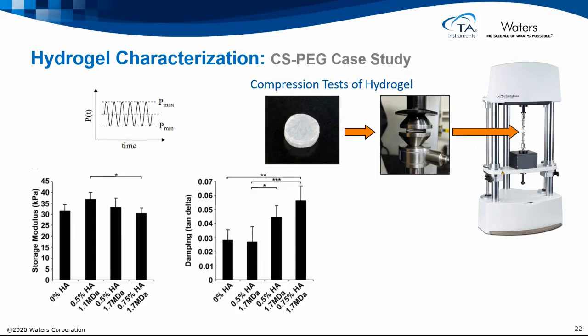Okay, here's a couple other results. This is a little bit more complicated yet. Before, we just did a compression ramp in displacement, which is strain, and measured the force, which is stress. Now they did an oscillating study. This allows you to oscillate displacement on this same material, a compression cylinder or disc, and measure the modulus by looking at the amplitude of force compared to the amplitude of displacement, or specifically the amplitude of stress divided by the amplitude of strain. That's a method to get the storage modulus.